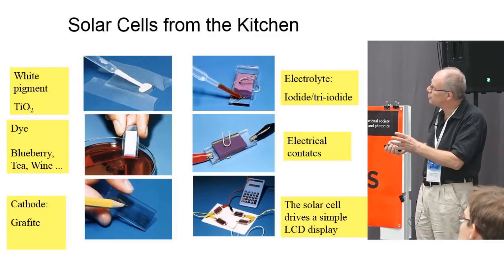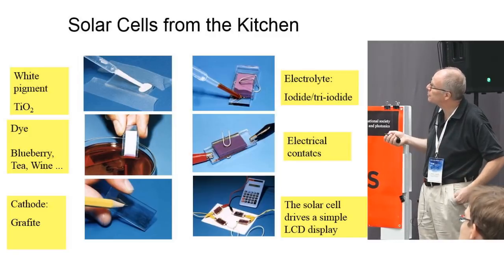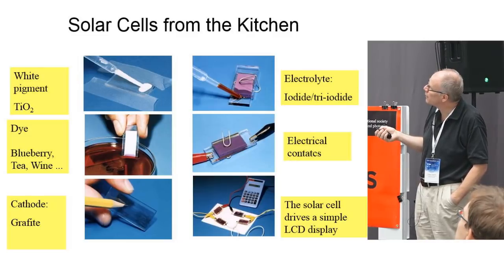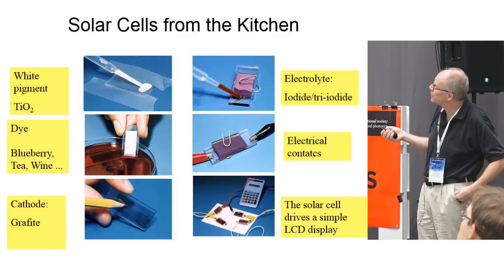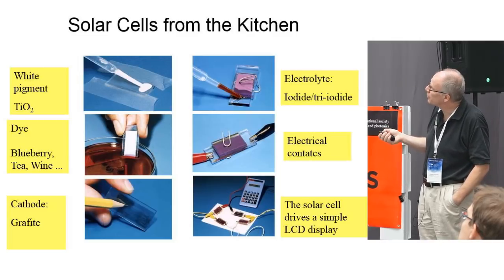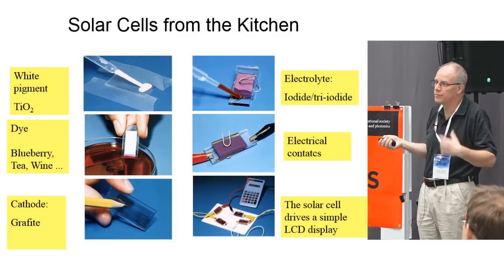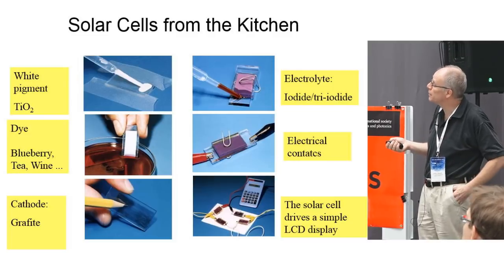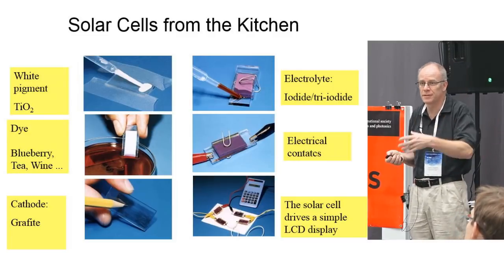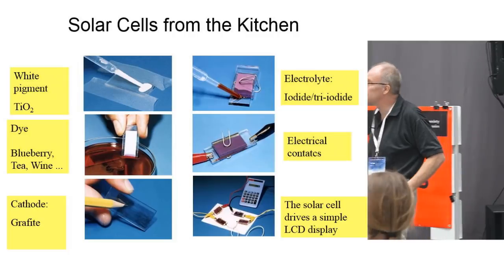Then you put your two glass electrodes together, clamp them, and fill up the interior with your electrolyte. So then you have an electrochemical cell, and then you apply your contacts and measure current and voltage when you shine light on it. So then you can see how good you are and measure your efficiency and so on.